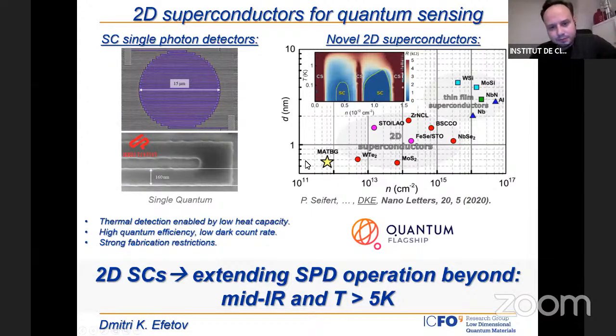There is a whole field, which is actually commercialized now, of superconducting detectors. Superconducting detectors, in particular single photon detectors, are one of the most sensitive detectors of quantum light right now, and they're used in all quantum optics laboratories at this point. These detectors depend on the heating of the superconductor. If you have a very thin superconductor and you absorb a photon, this photon can heat the superconductor and make it resistive, and therefore you can detect a photon. The ideal material for such detectors is usually the thinnest possible superconductor you can make, and also the superconductor with the lowest heat capacity.